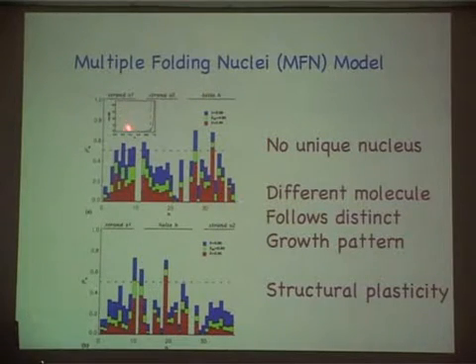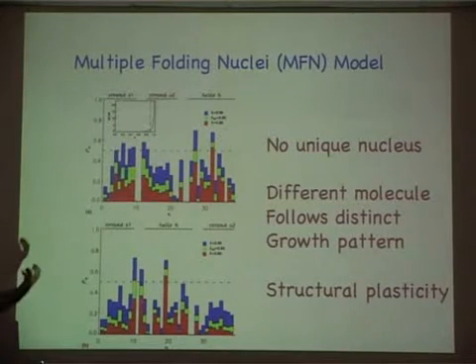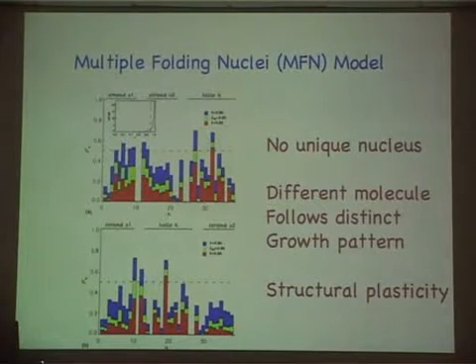In the inset, there is a progress variable that tells you how far the folding reaction has gone, and what the probability is of really reaching the native state in terms of this progress variable. And you see it's pretty much 0 till this progress variable reaches some value, and then it suddenly goes up. So something interesting is happening here on average. It is that region which we then say must correspond to the barrier crossing, in which you could have embryos of the native structure present for the first time.